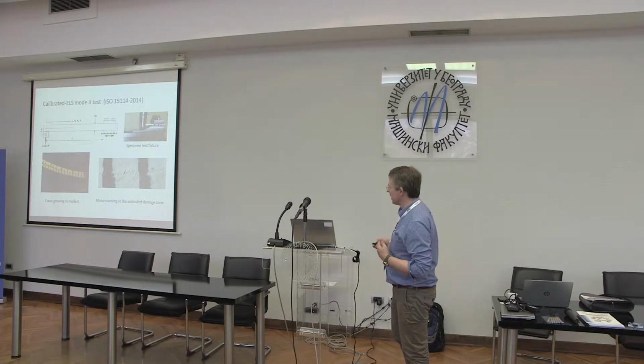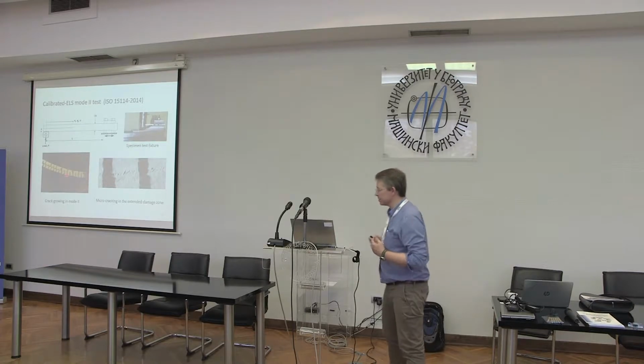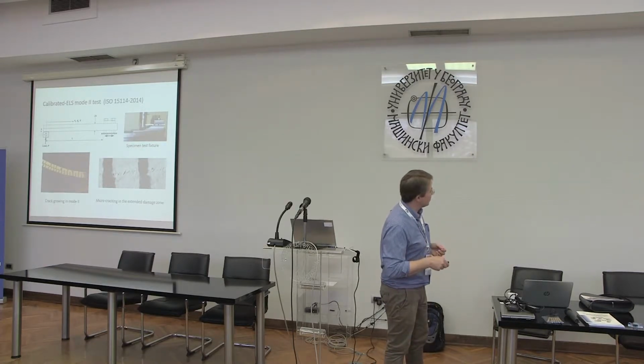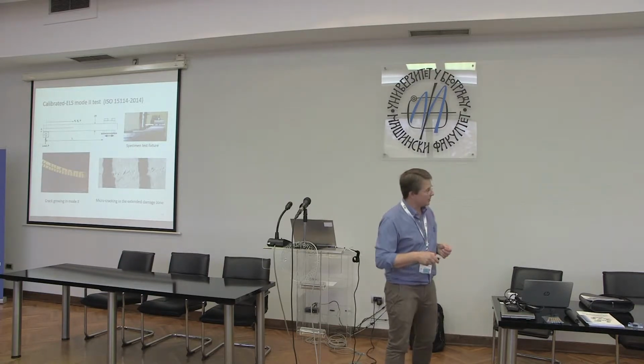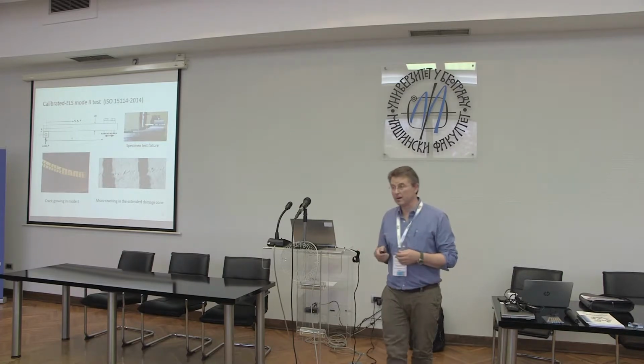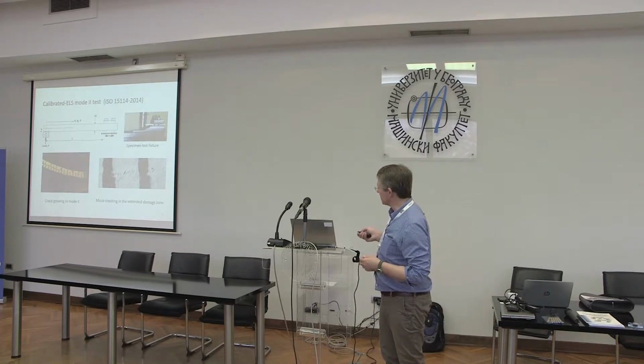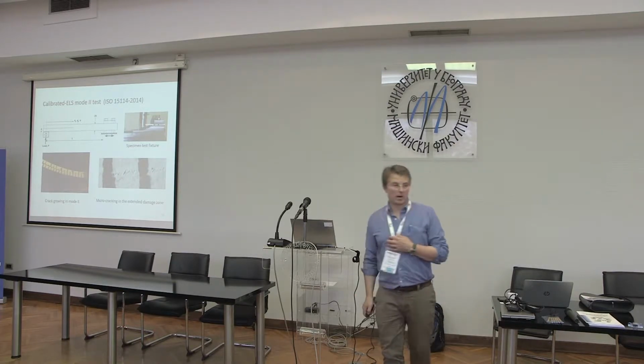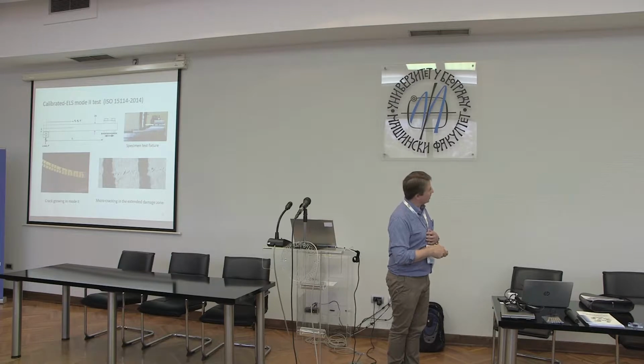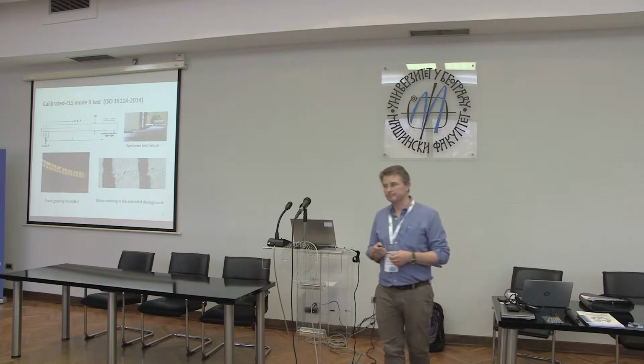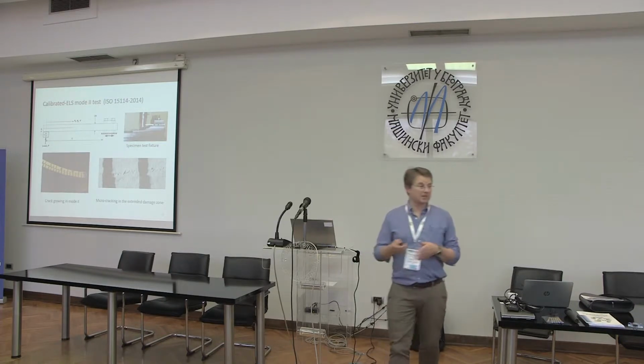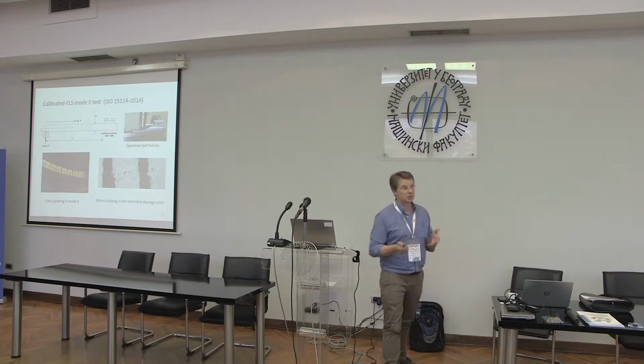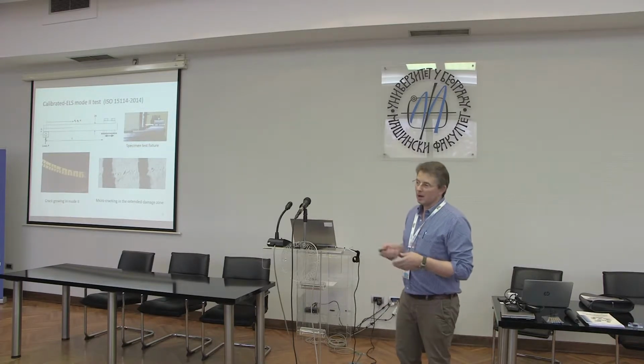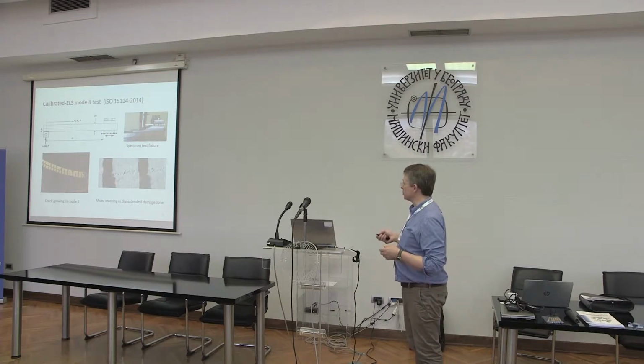It pulls on it. And this is a photograph of the crack growing in mode 2. So you can see that the crack grows, that the lines shear. And if you look very closely ahead of the crack, you can see typically a range of what we describe as micro cracks. So ahead of a main crack where you've got continuous delamination, you can have some discontinuous delamination. Now, when I'm talking about systematic defects, here's another example of a systematic defect. How do you approach this? How do you write into a standard methodology what should be measured?